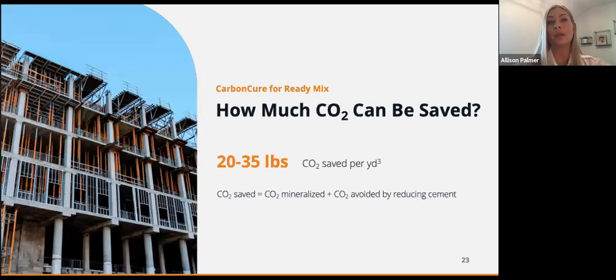So if you recall, that 1 ton of cement produced equals about 1 ton of CO2 emitted. So that's a huge impact. When we're able to reduce the cement content by about 5 to 6%, that's about 20 to 40 pounds of material, depending upon the mix. We can do an analysis on any given project if we know what mix design is being used and a rough estimate of cubic yards. But if you're doing any sort of back of the napkin math for some projects that are coming up, 25 pounds per cubic yard is a safe estimate to use.